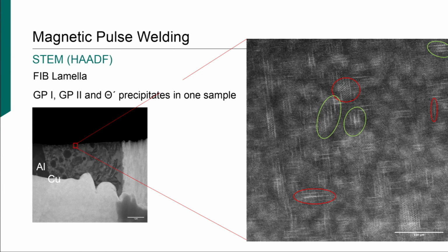long extension of the theta prime is, in my opinion, controlled by kinetics, that the adhesion probability is higher on the edges here than it is on the faces. Here this seems to be not the case. So you are highly out of equilibrium, and we're now trying to simulate or to reproduce this behavior